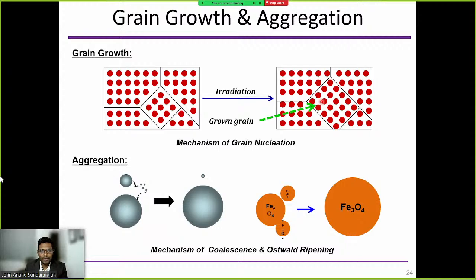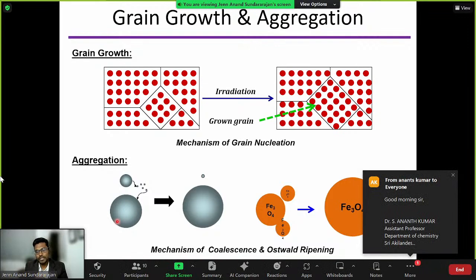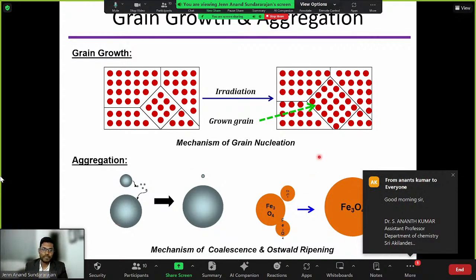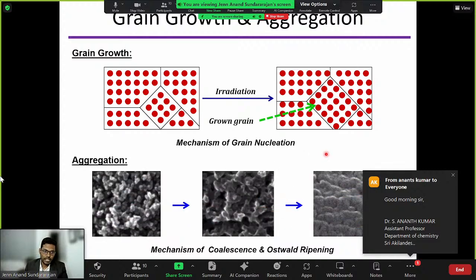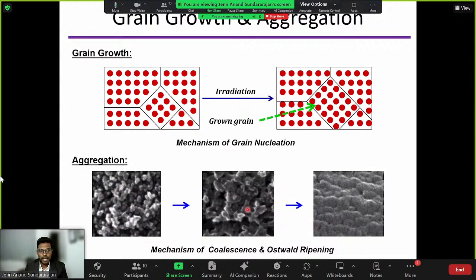Then aggregation also happens at the outset, because these are small, very fine particles. They aggregate together, coalesce together, that's the method of Ostwald ripening, and form bigger particles in here. And that's what we see here. As you can see, this is the in situ study result. As we expose it to more radiation, they agglomerate together.